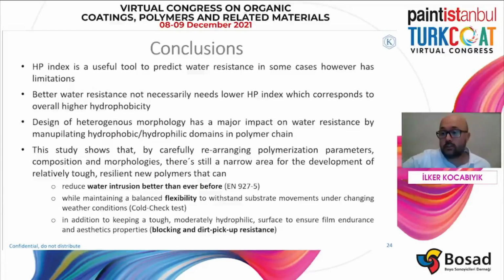Careful design of heterogeneous morphology has a major impact on water resistance by manipulating hydrophobic and hydrophilic domains in the polymer chain. Our study shows that by carefully rearranging polymerization parameters, composition and morphologies, there is still a narrow area for the development of a new acrylic polymer that can reduce water intrusion better than ever before, while maintaining a balanced flexibility to withstand substrate movements under changing weather conditions. In addition, it keeps a tough, moderately hydrophilic surface to ensure film endurance and aesthetic properties.